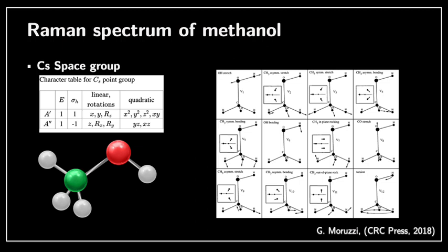And quadratic will tell you which of those modes behave quadratically. And it turns out for methanol, both the mode A prime and A prime prime correspond to quadratic terms, and therefore they are Raman active. So on the right-hand side, you do expect those modes to be Raman active.